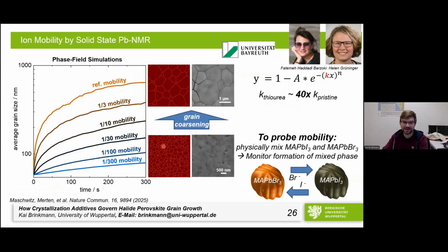And now we can have a look again at the grain boundary simulation that we had. So if we go from here to somewhere around down here, we would roughly need a factor of 30. And we're coming from grain sizes of maybe 120, going to average grain sizes of roughly 700, which is, I'm not sure, no, I didn't put the distribution here. We would have to go back for this, but this fits surprisingly well to the distribution and grain sizes that we have. So we ended up with basically discarding nucleation as the root cause for grain size, but that we have the grain coarsening, and apparently the ion mobility across the grain boundary is what makes it happen.